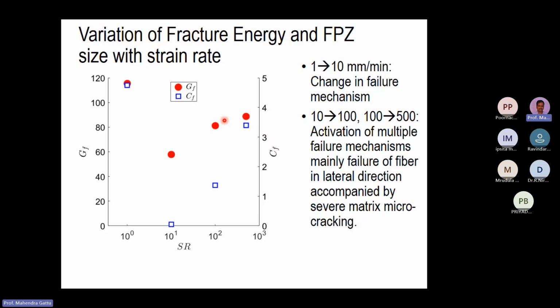And what we found was between 1 to 10 and between 10 to 100 and 100 to 500, the mechanism of failure in the composite material was different. Okay. So at these higher loading rates, say from 10 to 100 and 100 to 500, we found out multiple failure mechanisms, and the fibers in the lateral direction, that means perpendicular to the loading direction, they also started to fail. As a result, the FPZ size started to increase. Okay, so this was what we understood at that point of time.